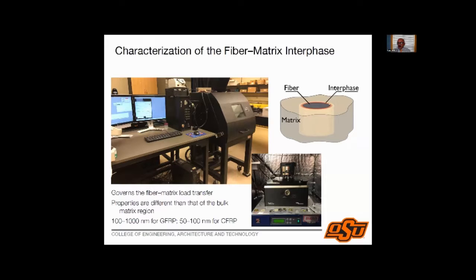But this interface is now responsible for the load transfer from the matrix to the fiber. So we want to try and understand the properties of this interface. Not only do we want to try and understand the mechanical properties of this interface, we also want to try and understand what happens to the changes in this mechanical property if I take this composite and subject it to some kind of environmental degradation, right? Carrying out mechanical tests at a length of 50 nanometers is very difficult. You can do indentation, but you cannot do regular indentation. You have to do indentation using an AFM.